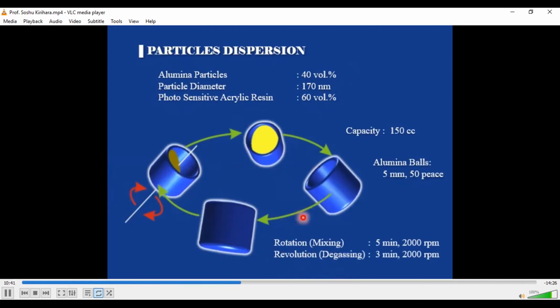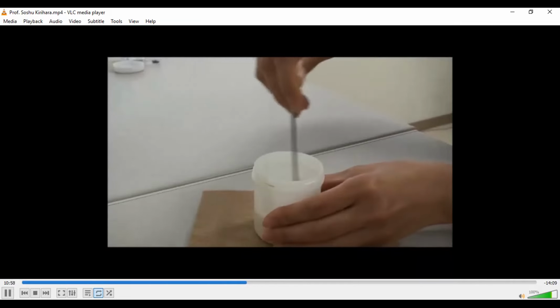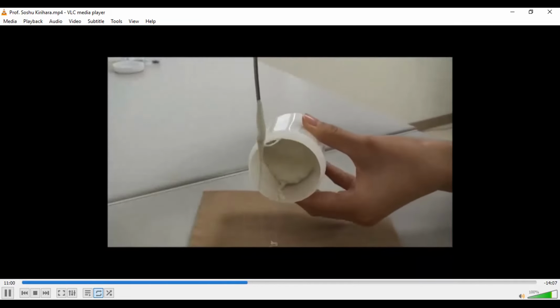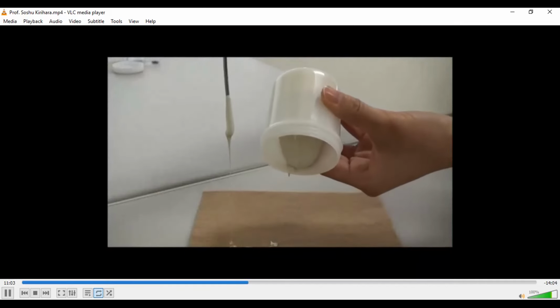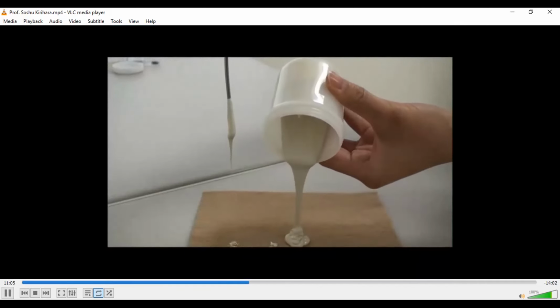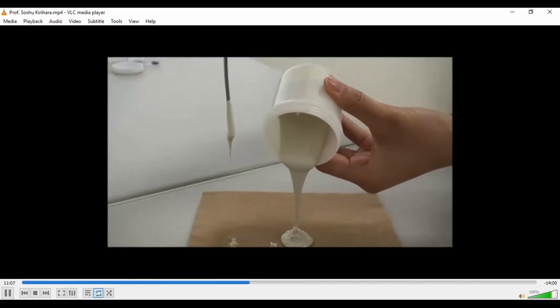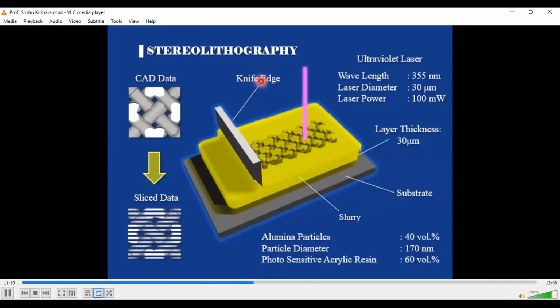This is a movie you can see. At first the paste material is very hard, with higher viscosity. However, if you introduce a stick and turn around the paste, you can see the paste material flows smoothly. Anyway, we can control the viscosity by introducing shear stress. So this high viscosity paste was spread on the glass substrate by using a mechanical knife edge, and in this case, the layer thickness is 30 microns.